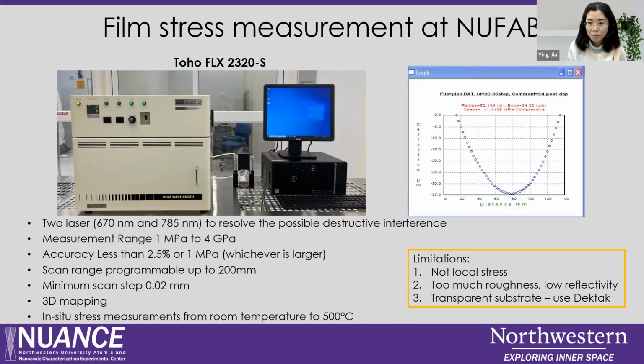I have one question for this stress measurement. What is the spatial resolution? For example, how large? The minimum scan step is 20 micrometers in the lateral direction. For the sample size, we recommend a 4-inch or 6-inch wafer, but this system can handle any size up to 8-inch.